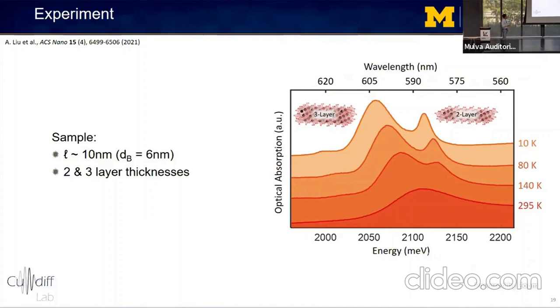And for reference, the lateral dimensions of our nanoplatelets are around 10 nanometers, which is quite large compared to the exciton Bohr diameter of cesium lead bromide in 2D of 6 nanometers. So it's clear that the dominant quantum confinement is from the out-of-plane thickness. However, variations in the lateral confinement can still introduce inhomogeneous broadening of your exciton resonance.